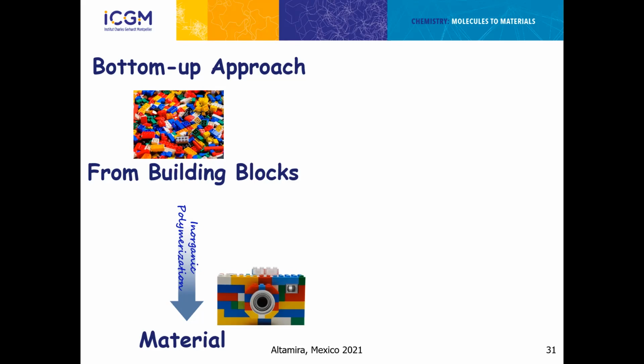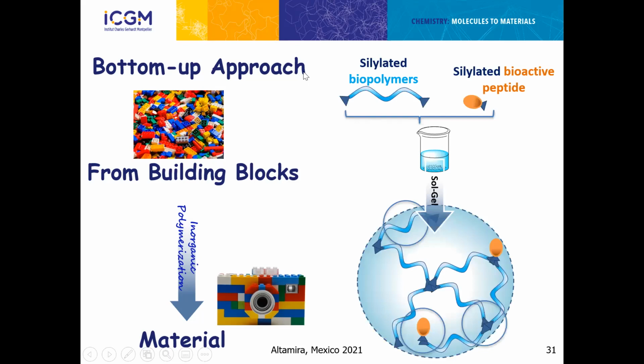If you add one functional group, maybe you have functionality, but it's possible to add 2 functional groups, 3 and 4, and so on. Here I put just 2 functional groups, just the biopolymers and peptide, but it's not forbidden to add another type of molecule silylated. You can add a dye, you can add another type of biopolymers. You can prepare a big cocktail, and you can hydrolyze and polymerize all together, because the kinetic is the same. All the polymerization takes place at the same time. So the idea is to prepare hydrogel in one step.